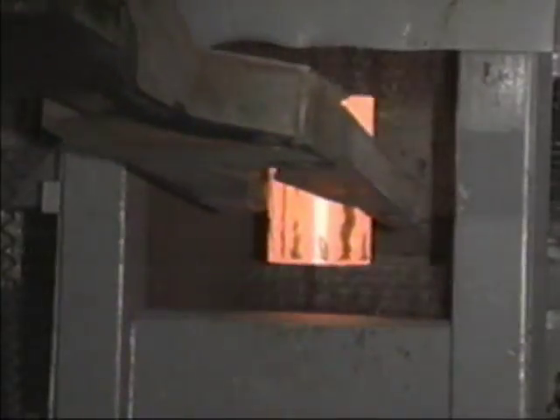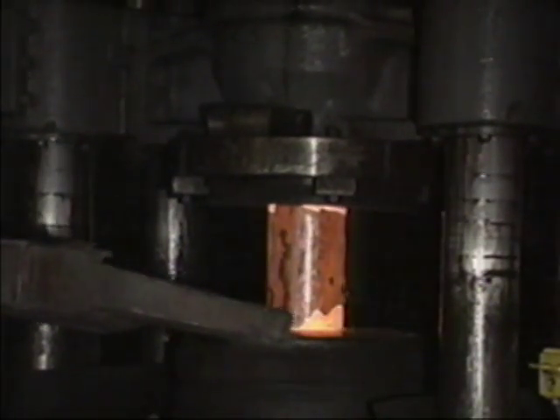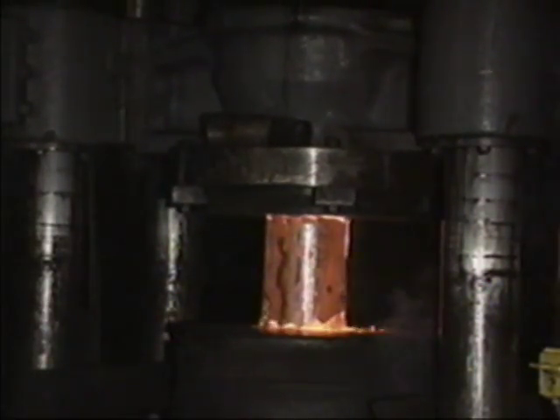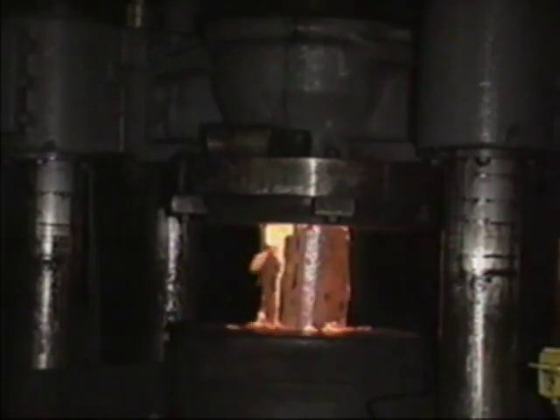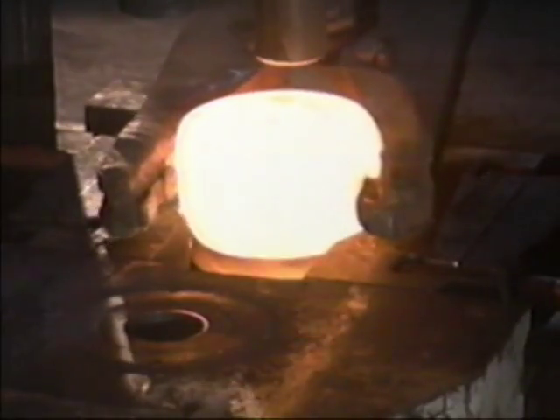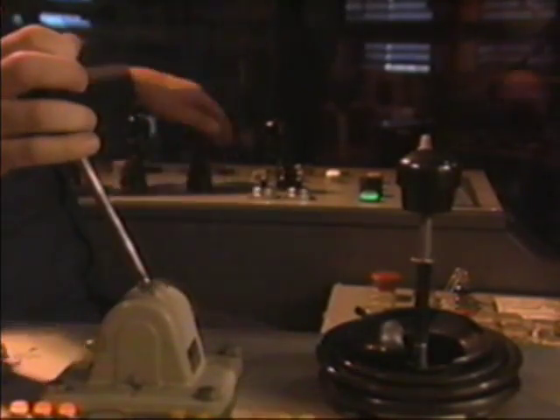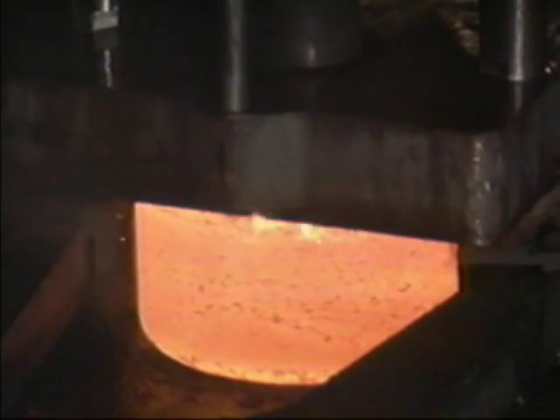During the heating process, scale forms on the outside of the blocks. This scale is removed from the ends of the block by means of a chain descaler. The block is then upset to a predetermined height on a 1,000-ton press, thus removing the remaining scale. The preform is then transferred to a 2,700-ton two-station blanking press, where it is first indented, then it is pierced, producing a finished blank.